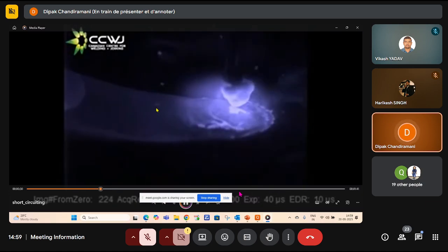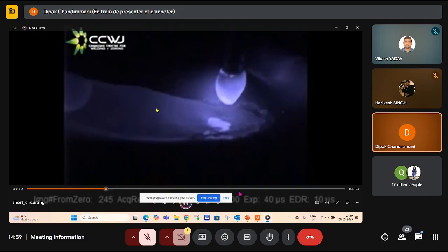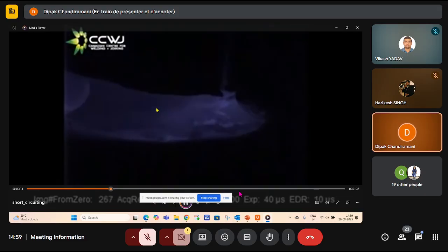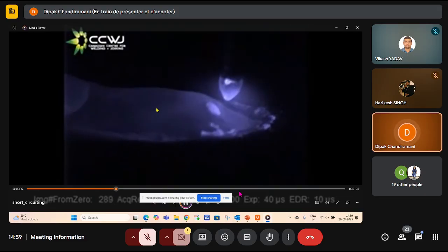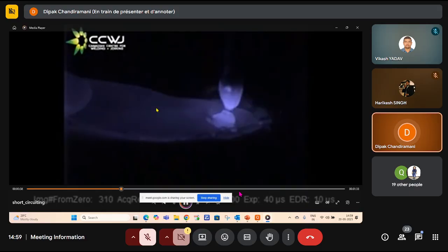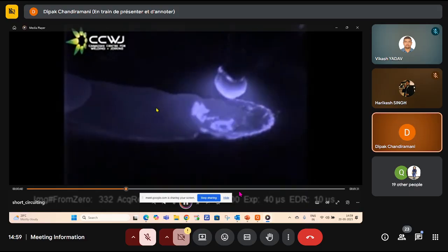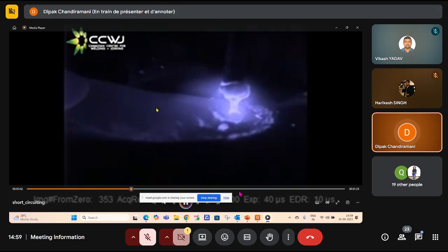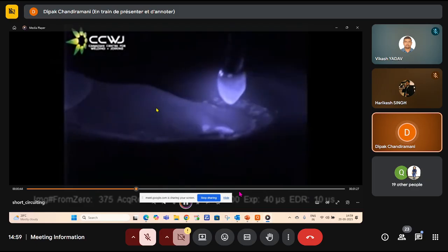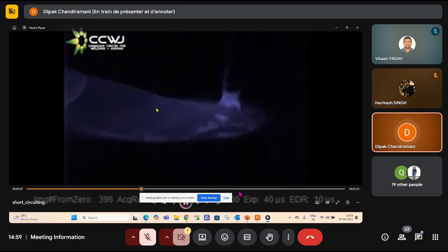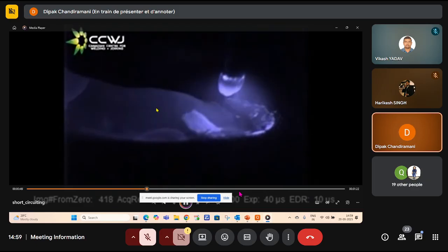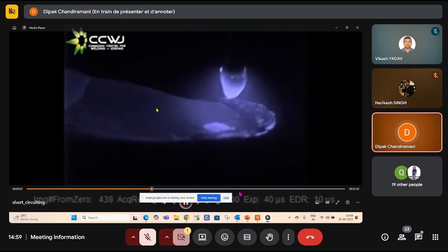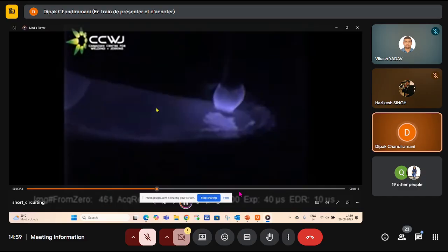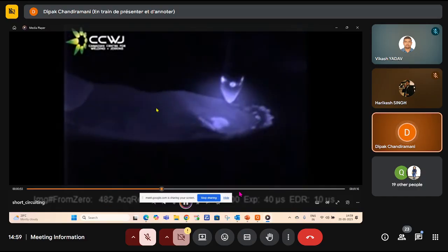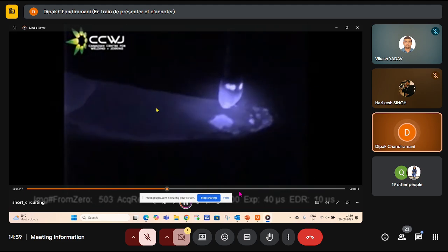Now this is happening 150 times a second. These are very high speed. So ultra slow motion pictures have been taken, but this is happening so fast you couldn't see it otherwise. And because there is no arc here, the heat input is less. Because heat input is less, there is possibility of lack of fusion. So when he says qualifying by short circuiting, you must qualify by bend test only, not by RT. RT will not show you the lack of fusion if it's there.